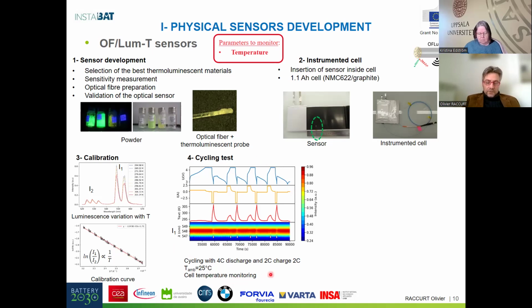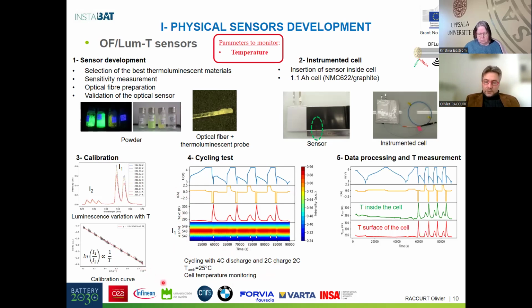It's what we show in this graph, where we tested the cell in a 2C charge and 4C discharge cycling. And you can see here the variation of the intensity of the peak 1 during this cycling, and we observe that the intensity decreases when the temperature increases. And if you apply the calibration curves, you can access the internal temperature of the cell. And if you compare this internal temperature in green to the surface temperature measured by the thermocouple, there is a very good correlation of the signal between both measurements of the temperature. And this result validates the behavior of the sensors, and the sensors work very well inside the cell without any modification. I don't show here the result, but there was no modification of the performances of the cell in terms of electrochemistry.